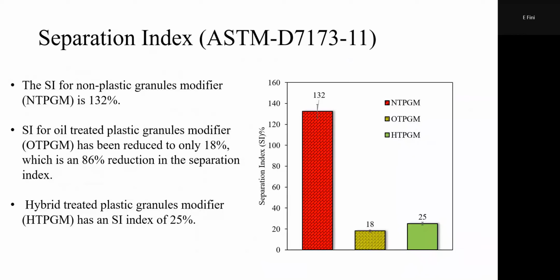That means they separated. So in this case, the non-treated one, which I showed you in the beginning, separated big time. That's the red line, 132% different between bottom and top. So if it was a cup of coffee, it would be very bitter on the bottom, or the reverse, sweet on the bottom, bitter on the top. In this case, the change was just not acceptable. These two are incompatible. You could just mix it and think you did a good job. You added all this waste plastic into asphalt, but your pavement will be terrible. It's going to crack as soon as you place it and compact it because they don't like each other.